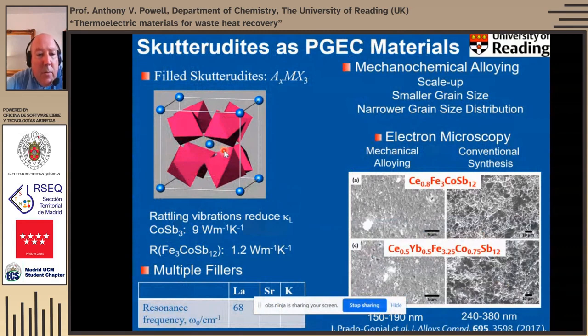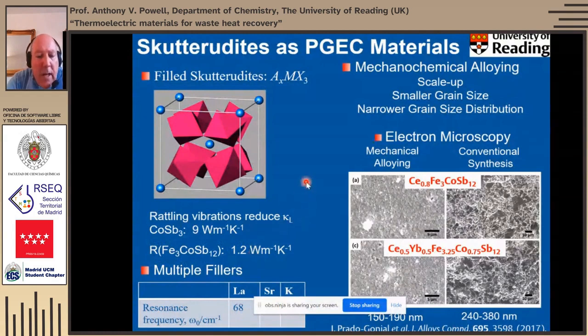If we introduce some rare earth cations into that cavity space, we have to adjust the electron count of the host as well. So we have to replace quite a lot of the cobalt with iron in order to maintain the appropriate electron count, because the rare earth is, of course, donating 3 electrons when it goes into that cavity. We can reduce that thermal conductivity by about a factor of 8 or so. And that can give rise to quite significant performance enhancements.